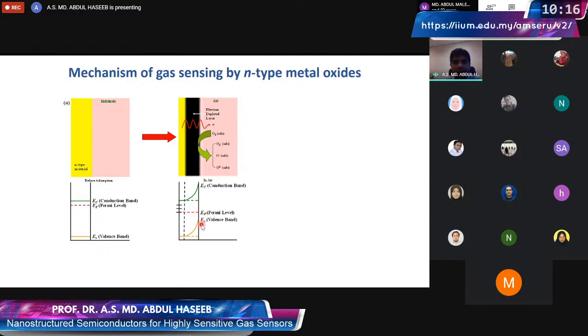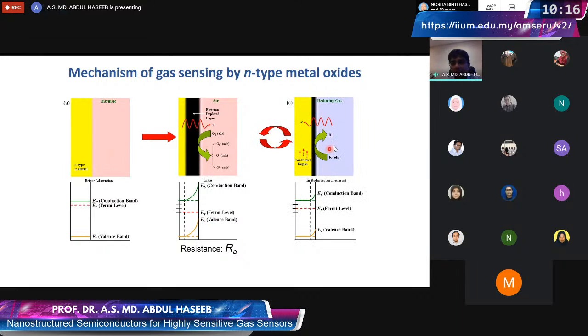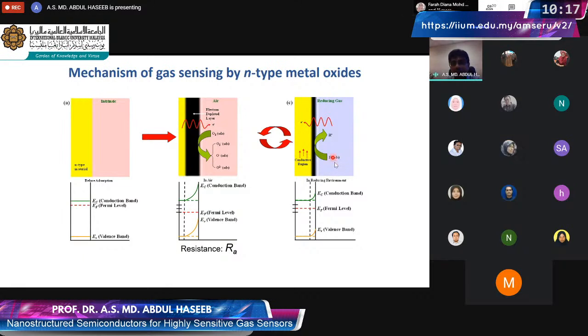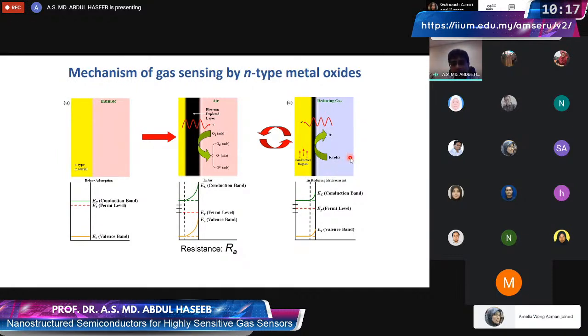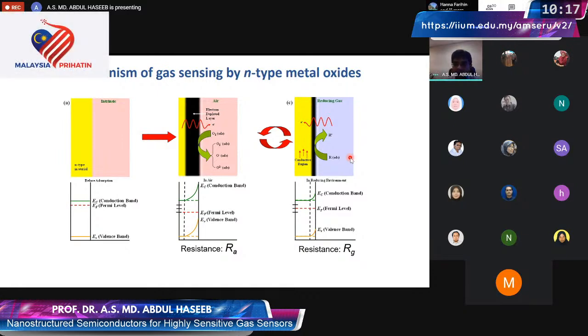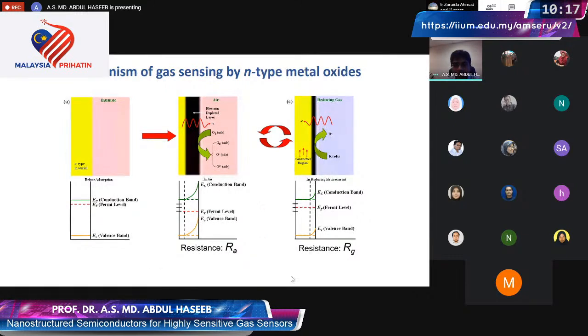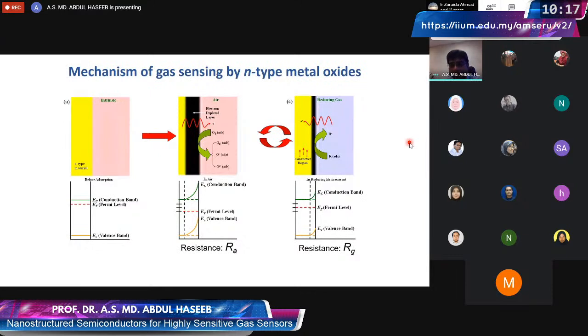Now, if in the air we have a gas that we want to detect, and let's say this gas is a reducing gas, then the reducing gas will interact with the semiconducting surface. The reducing gas will donate electrons to the surface of these N-type metal oxides. And as a result, the depletion zone will decrease in its width, and the resistance of this material will decrease. And if we measure the resistance in a particular gas, then we have two quantities now. One is Ra, which is the resistance in air, and one is Rg, which is the resistance in a particular target gas. And Ra is obviously greater than Rg.